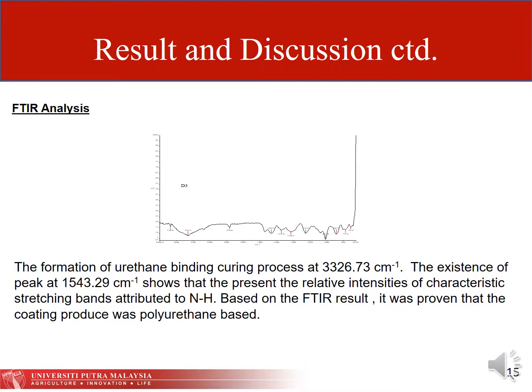Comes to FTIR analysis, the formation of urethane bonding during the curing process is seen at 3326.73 wavenumber. The existence of a peak at 1543.29 shows the presence of relative intensities of the characteristic stretching band attributed to NH. Based on the FTIR result, it was proven that the coating produced was polyurethane based.